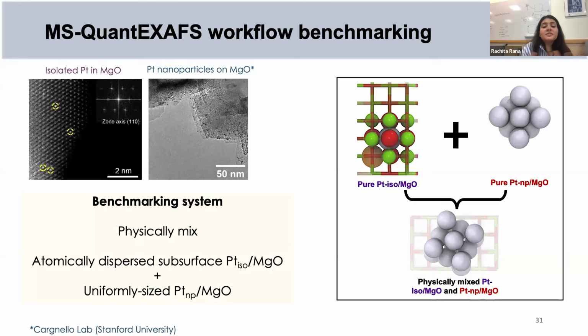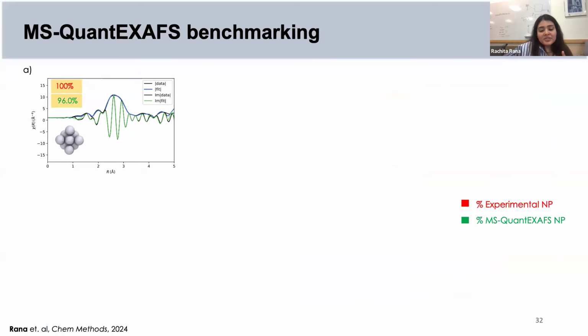And then we made a physical mixture of these two samples in different fractions. So we had known fractions of each of these, and we went to the beamline and collected our X-ray absorption spectroscopy data at cryogenic temperatures. The idea was to see whether MS-QuantEXAFS would be able to predict what fraction of a specific structure is present in the experimental EXAFS data in this benchmarking system.